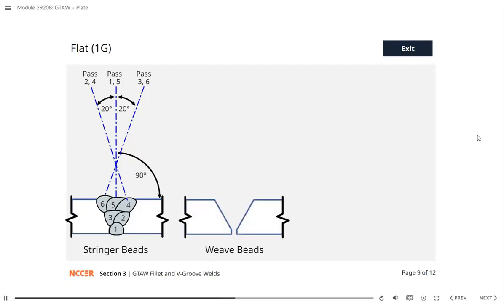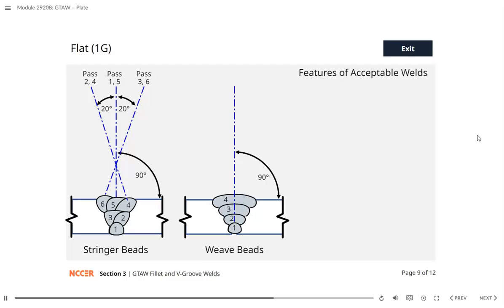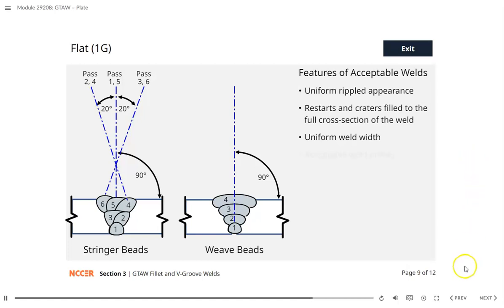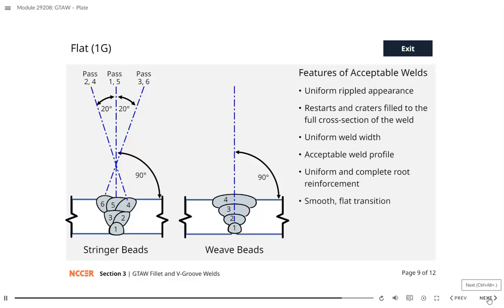Weave bead passes will follow a different sequence, as shown here. Finish by inspecting the weld to ensure it meets acceptable criteria, such as a uniform rippled bead face appearance, restarts and craters filled to the full cross-section of the weld, uniform weld width, an acceptable weld profile, uniform and complete root reinforcement, a smooth, flat transition, and undercut within specifications. Also, ensure that there is no excessive porosity or cracks.